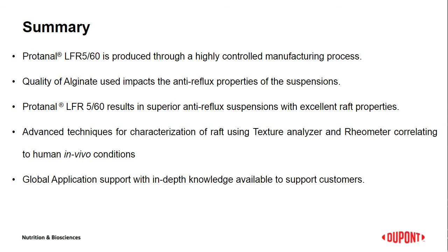So in summary, we conclude that Protanal LFR 5/60 sodium alginate is produced through high control procedures. The quality of the sodium alginate used in anti-reflux suspensions impacts the raft properties. The characterization of the rafts using the texture analyzer and rheometer, correlating to the in-vivo conditions, shows that Protanal LFR 5/60 results in superior anti-reflux suspensions with excellent raft properties.